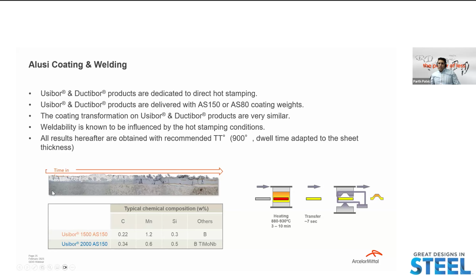What happens is when we supply raw material to the hot stamper, they receive it in an Al-Si coating, and when they start heating in the oven, transformation occurs. When it's fully alloyed, it looks similar to this in the picture - you'll have an ideal interdiffusion layer and a fully alloyed coating. This is what the welding or assembly guy deals with. That's the key - weldability is influenced by the coating, and ultimately influenced by the hot stamping condition. So we have to keep in mind that hot stamping conditions really matter for the welding.